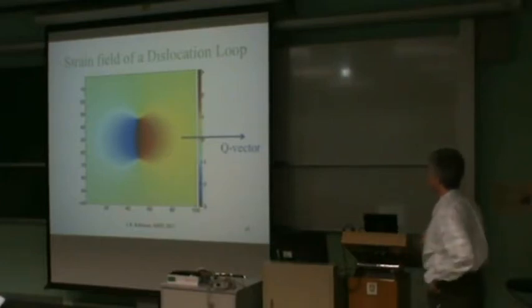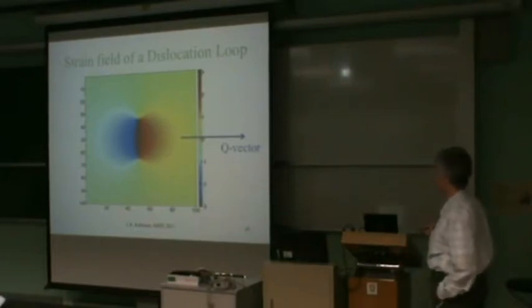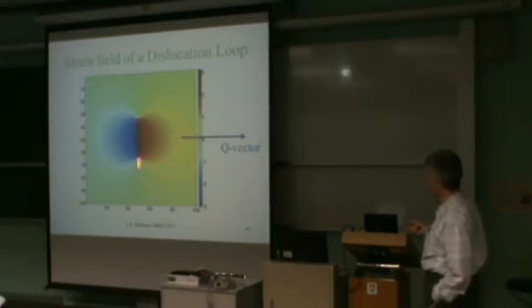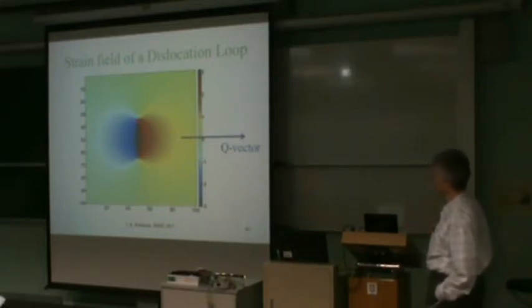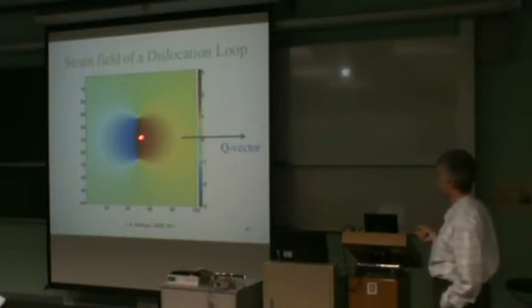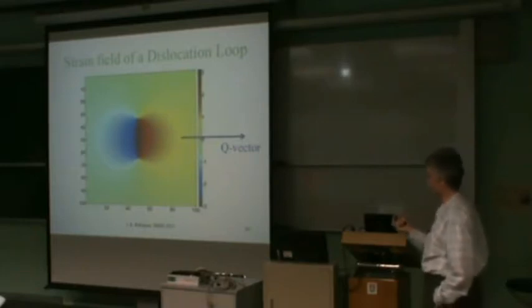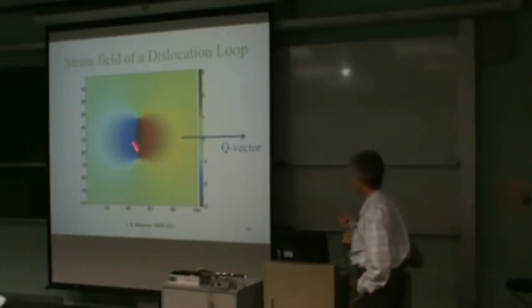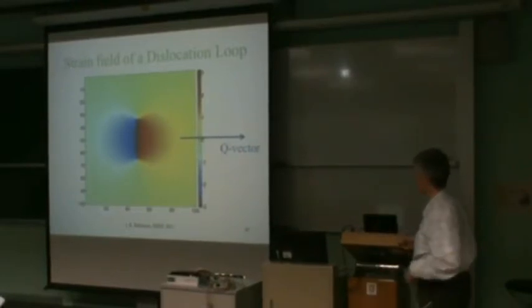And the third example is, and I'll show this a little bit later, but this just shows what we're expecting to see. If you have a dislocation loop where you have a screw dislocation coming out of the plane on this side and going into the plane on that side due to the presence of a missing plane of atoms in the center, or an inserted plane of atoms in the center, then you get a very clear dumbbell-shaped diffraction pattern, which has got a phase of pi on one side and minus pi on the other side, that corresponds to the presence of an extra plane of atoms which is inserted and associated with the dislocation loop.